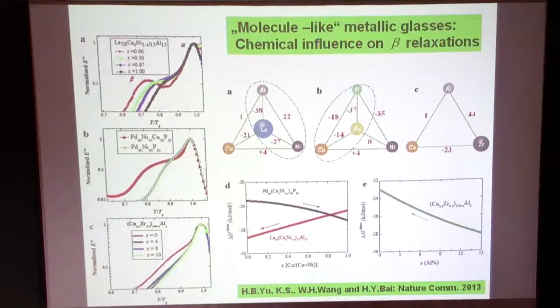Yes. So you say there is something which is loose with a certain condition? The idea is the following. You form clusters in the liquid. These liquids have certain polyhedra, icosahedra, different kinds of polyhedra. And now those are the stable elements, the motifs which you try to understand. And these motifs then either join together and form a very rigid matrix in the background, or you cut them up into certain segments and they are very loose, and these are the areas where you have the soft spots. That's the idea.